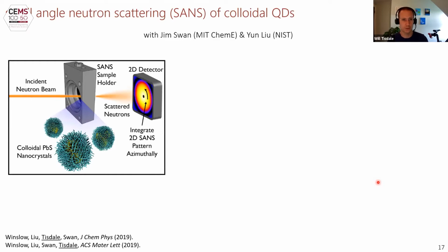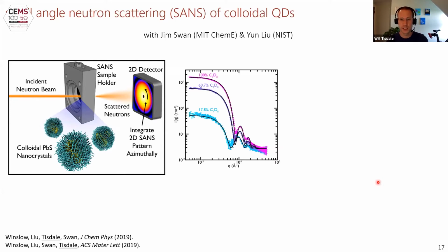The experiments are relatively simple. We go to a neutron scattering beamline. We look at colloidal dispersions of our lead sulfide quantum dots coated with, for instance, oleic acid on the surface, an 18 carbon chain with a single double bond in it with a carboxylate linkage to the surface. They're usually dispersed in toluene. We collect the 2D scattering pattern and then we analyze it. Here's an example of what the data look like.